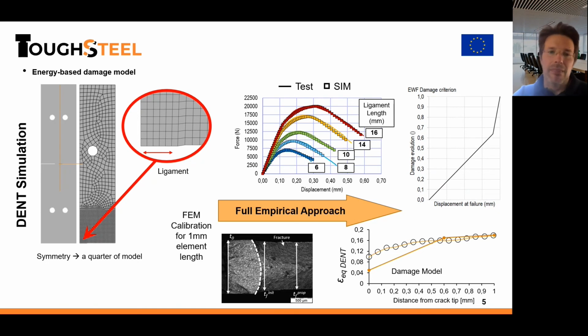This is a fully empirical approach, but in our latest investigation, we are observing that the values of the failure model are quite similar to the thickness strain at the crack tip, and we are working to propose a physical sense for our model. Like presented previously by David, we have a measurement of the thickness in the cracks for the test and also for the hole expansion or for cracks in the real component, and it is very similar to the values in the damage evolution model.